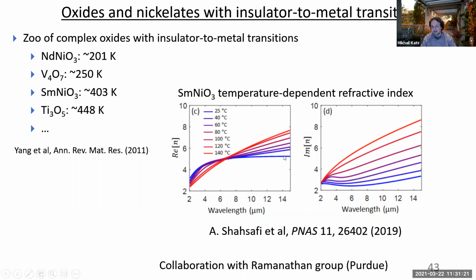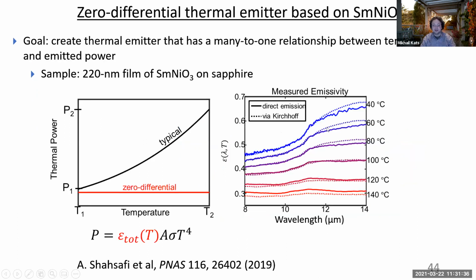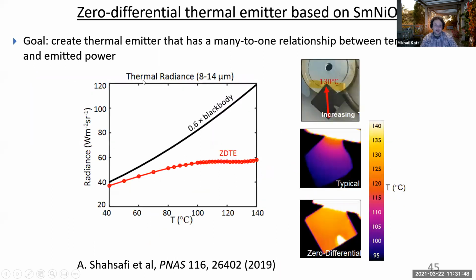When we did spectroscopic ellipsometry to characterize the optical properties, we saw that the optical properties changed, like in the case of VO2, quite dramatically, but not nearly as dramatically as VO2, as a function of temperature. That was exactly what we needed, because we needed an emissivity which changes with temperature in just the right way to cancel out the temperature dependence of the Planck and Stefan-Boltzmann laws. And so we were able to do that. Here is a result from this PNAS paper in 2019.